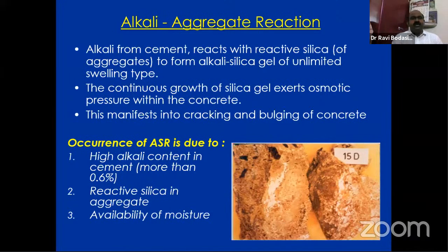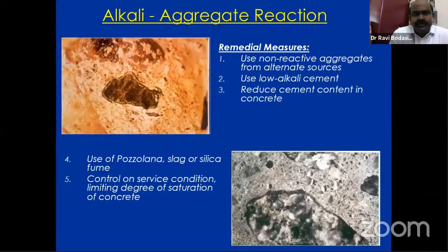So alkali silica reactivity occurs due to high alkali content in cement. As per the specification, it is limited to 0.6% only. Reactive silica, why? Because we cannot control the silica content in the aggregates, as these are all natural products which we are crushing and using.